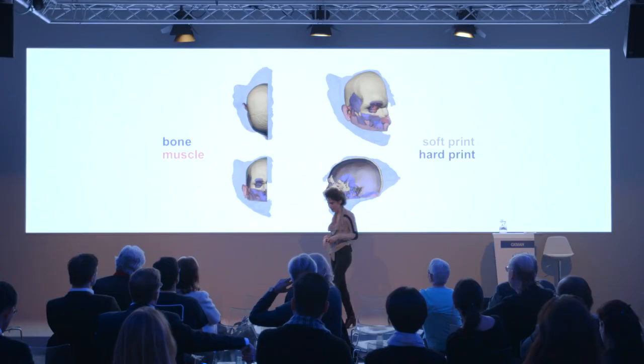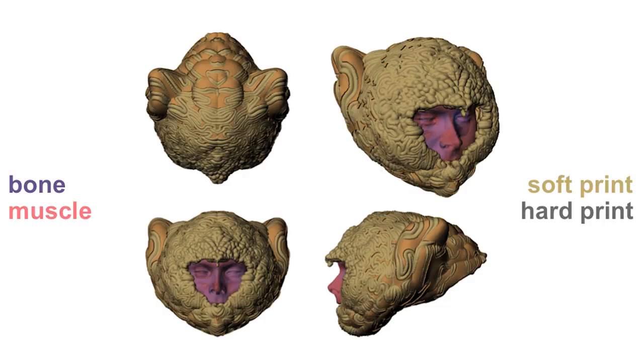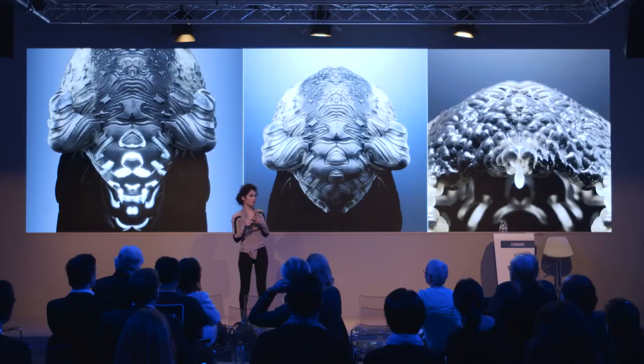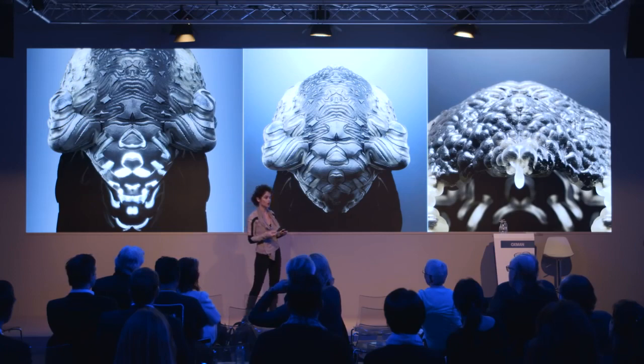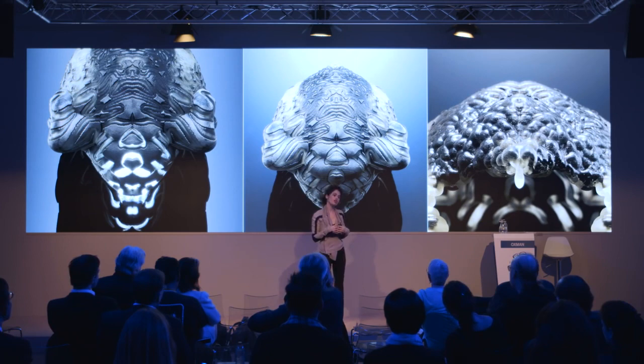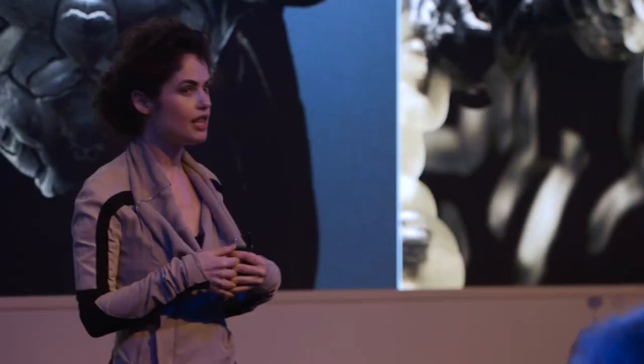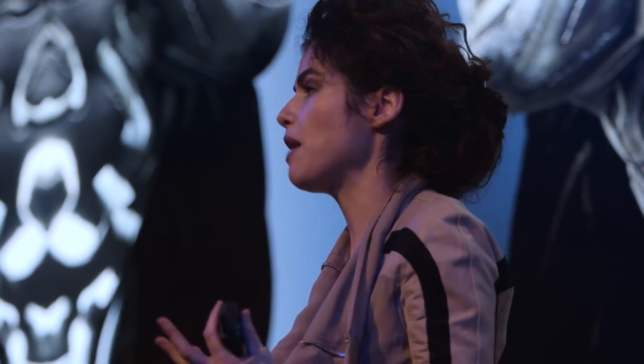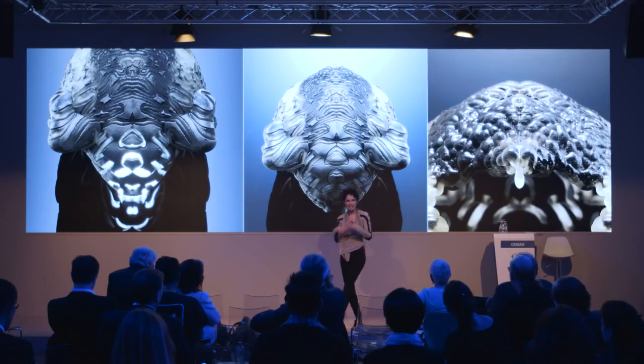Another project was a helmet designed for my head — though it can be designed for any head. Its design is interesting because it allows us to design not only for the shape of the head but also for the material composition. Rather than only taking the head's geometry as input, we take as input the physiological components that make up your bone, fatty tissue, and muscle tissue, and respond to that in very high resolution — 16 micron voxel resolution, the diameter of the human hair and the largest mammalian axon nerve ending. We can map between a CT scanner and a 3D printer, mixing and fusing stiff and soft materials together.